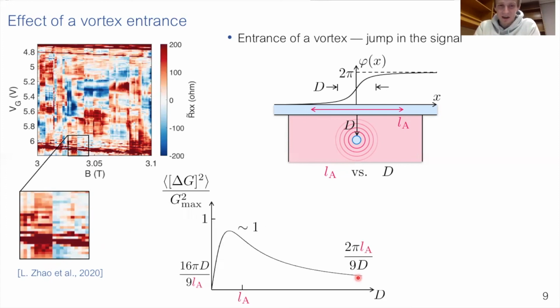To find this typical magnitude, we calculated the expectation of the squared jump. And here is our result. So we see that according to this picture that I outlined qualitatively, the typical value of the jump is small on both ends, both when the distance by which the vortex has entered is small and large. And in the middle, it reaches a value that is of the order of the signal itself, which is kind of interesting. So for appreciable jumps to happen, the vortex has to enter by a distance of the order of the Andreev length. And apparently this is a regime that is seen in the Duke data.